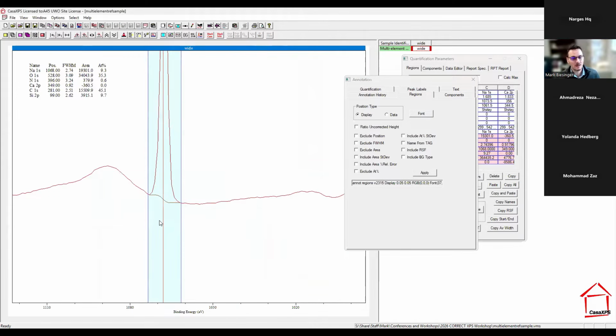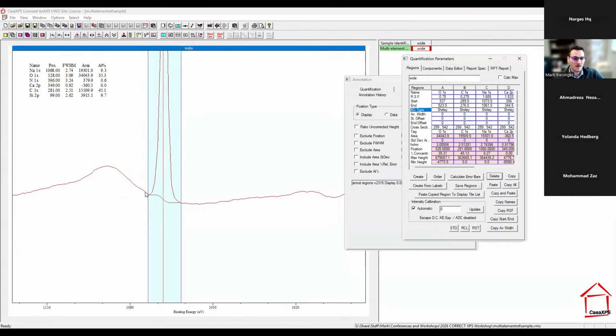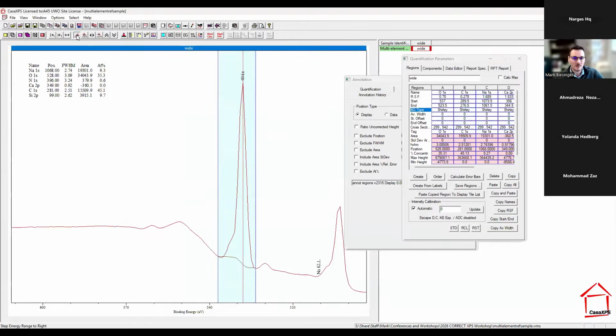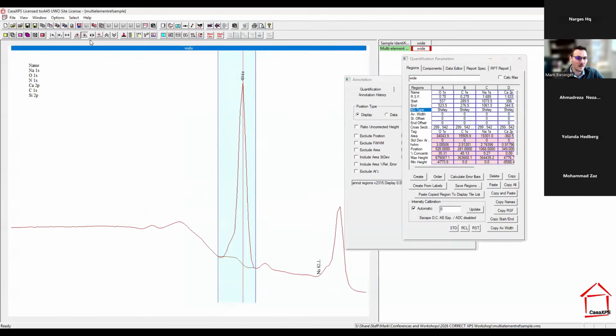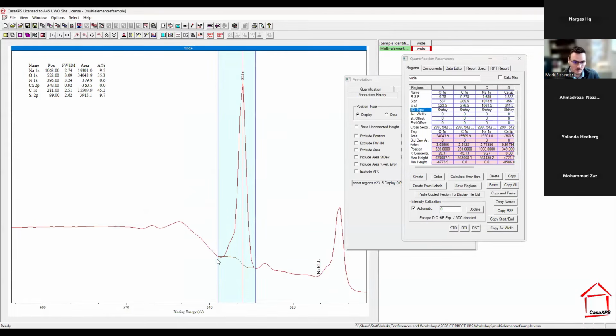So if we zoom in, we want to make sure our background across this, and here I'm using a Shirley background, has endpoints that look good. So it looks good there for that sodium peak. We just move on down the way to see what else we have. You can see here this oxygen peak, we're probably not getting right at the baseline, so we're going to move that a little bit so that it goes across the peak quite nicely.